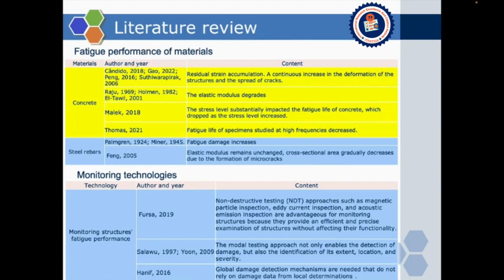For steel rebars, the study showed that the cumulative fatigue damage to the reinforcement was linear under the action of steady high cyclical stress amplitude. Under the action of steady high cyclical stress amplitude, the elastic modulus of the steel bars remains unchanged, but their cross-sectional area gradually decreases due to the formation of microcracks, resulting in their instantaneous brittle fracture.